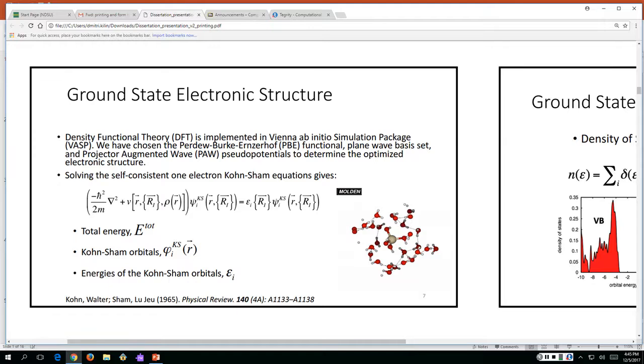This is an incomplete slide. But when we're thinking about what happens to an electronic structure when the system is confined, we end up with larger energy spacings within the material. This discretization of states prompts the opening of band gaps and increases the energies between adjacent electronic states, which also affects rates of non-radiative relaxation. A second thing is that because these materials become so small, they can get to a size smaller than the exciton Bohr radius. This is the relative size of an excited electron and hole.